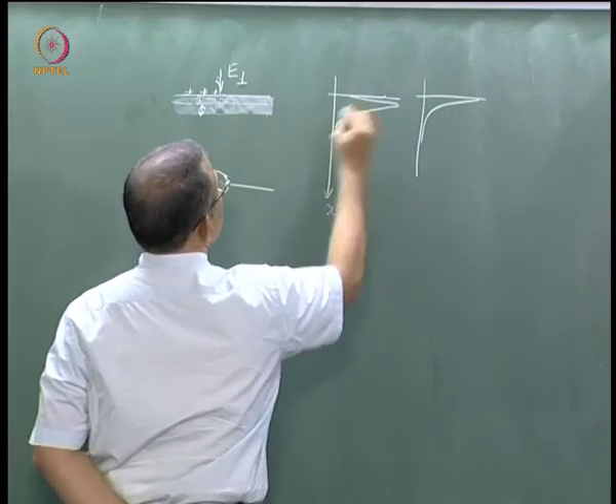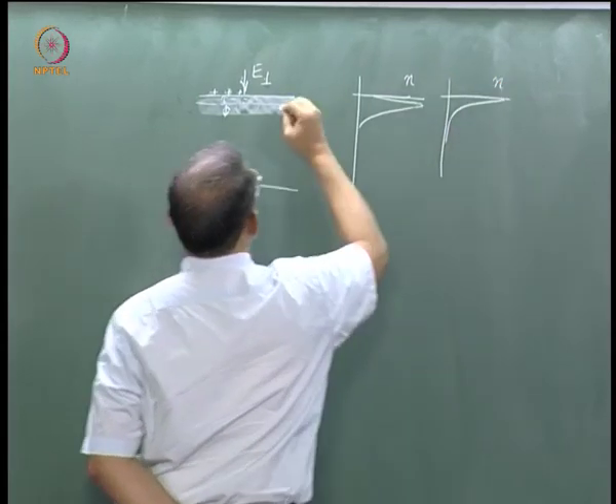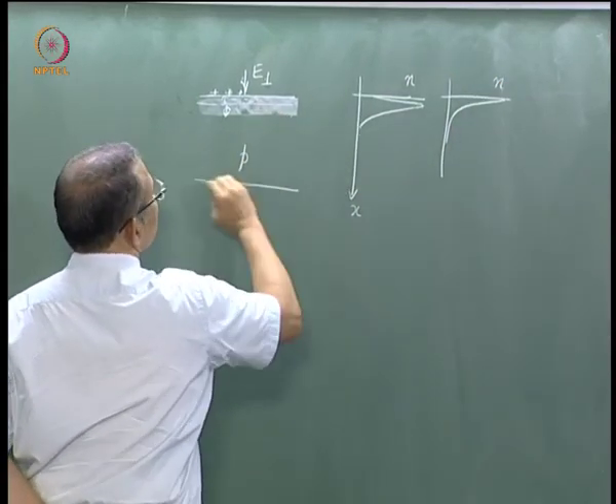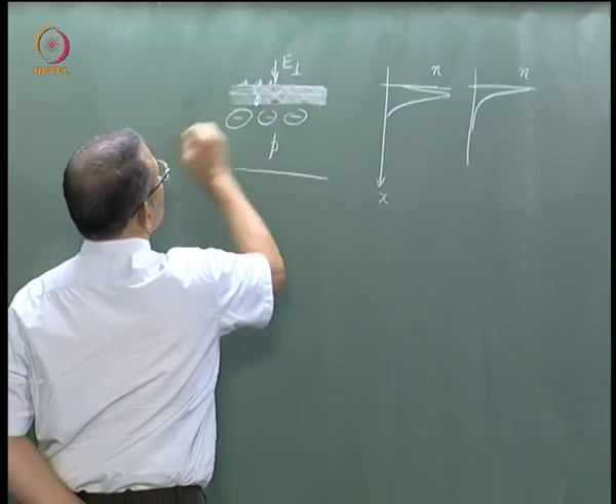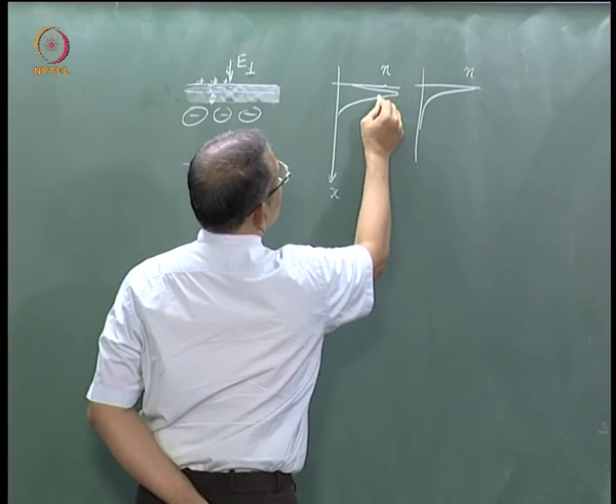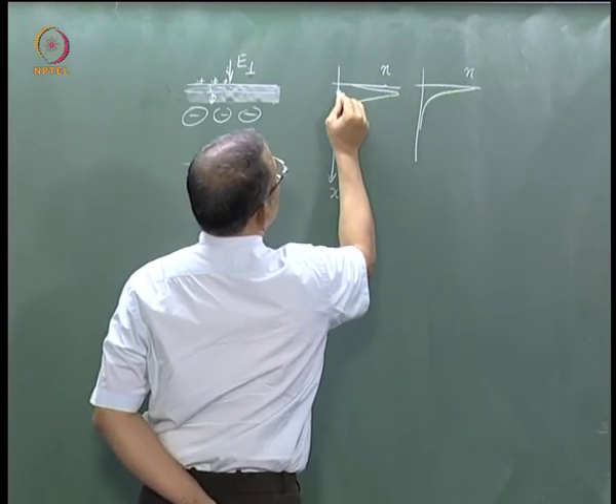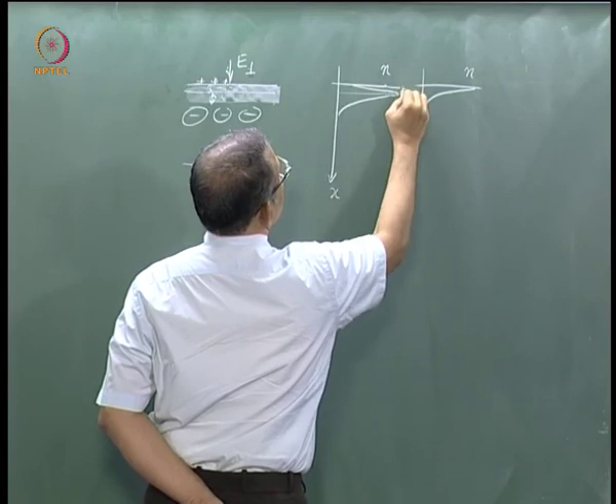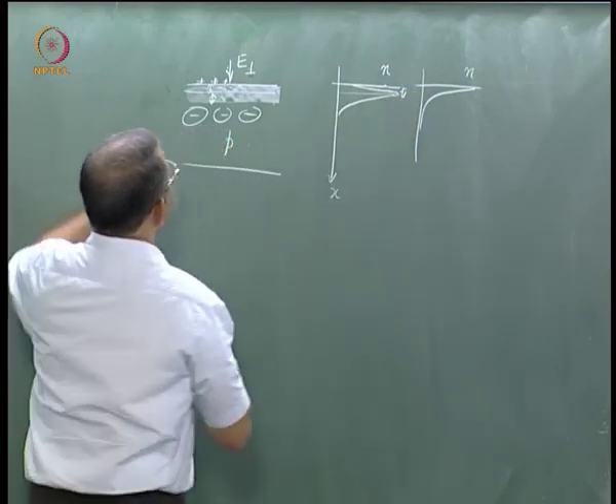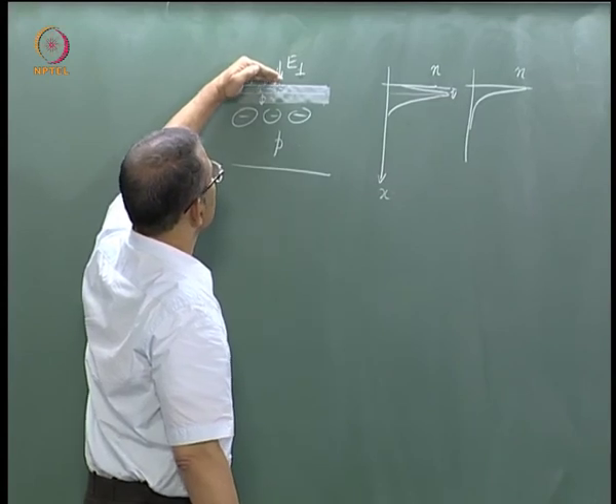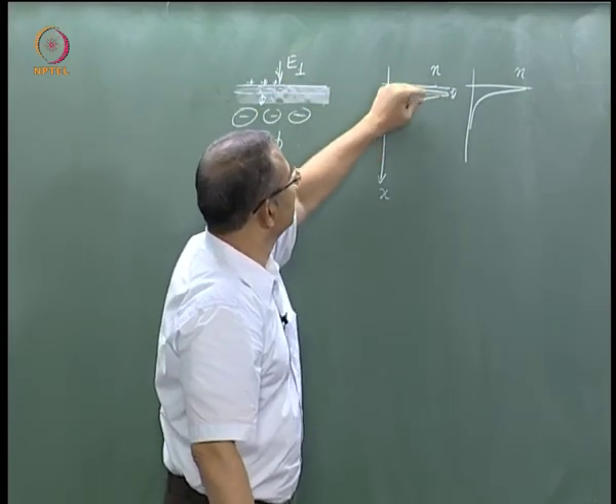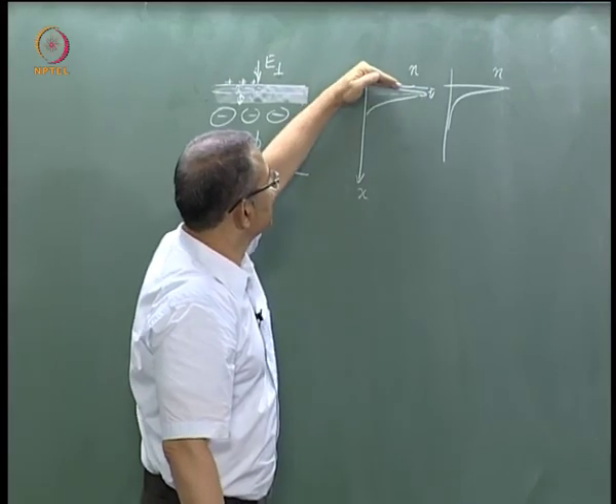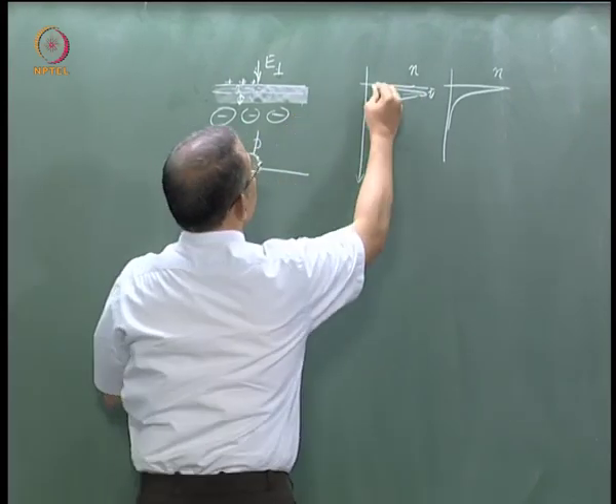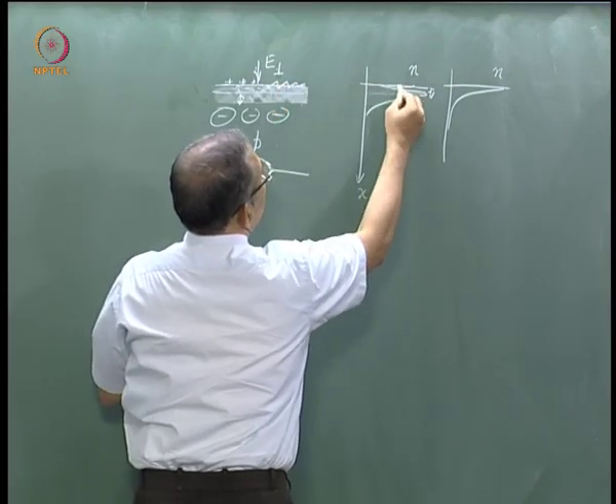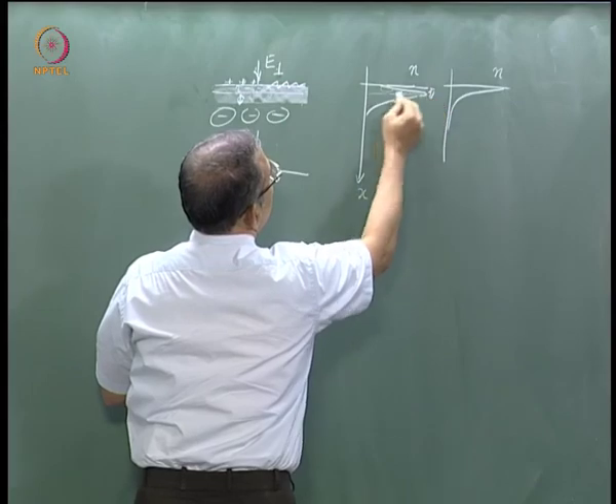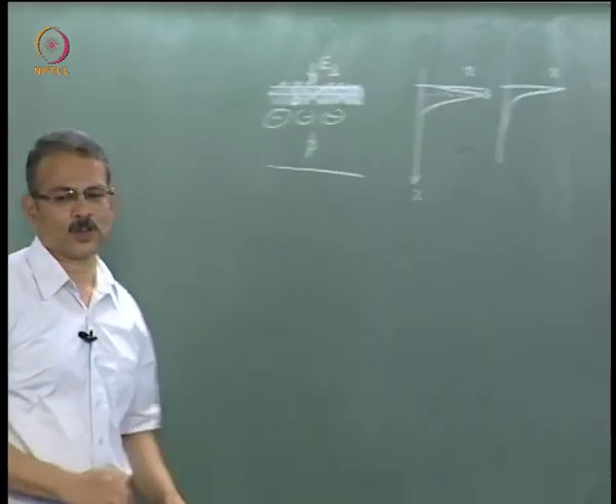So this is in the x direction, and what we are plotting is, let us say, electron concentration, okay, let us say p type substrate, and this is the inversion layer. So beneath you have a depletion layer also. Now it is like this, not like this. So you see the peak is away from the surface by this much amount, and that is why the effect of all these interface effects and so on will be reduced, because the peak is away. Many mobile carriers are away from the surface. Surface roughness effect also will be reduced, right. So if this surface is rough, it may have an effect on these charges, right, but not on these which are inside. So that is what is implied there.